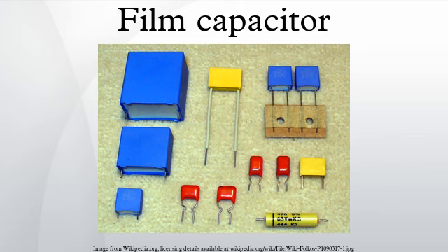PET capacitors are mainly used as general-purpose capacitors for DC applications, or for semi-critical circuits with operating temperatures up to 125 °C. The maximum temperature rating of 125 °C also allows SMD film capacitors to be made with PET films. The low cost of polyester and the relatively compact dimensions are the main reasons for the high prevalence of PET film capacitors in modern designs. The small physical dimensions of PET film capacitors are the result of a high relative permittivity of 3.3, combined with a relatively high dielectric strength leads to a relatively high volumetric efficiency.